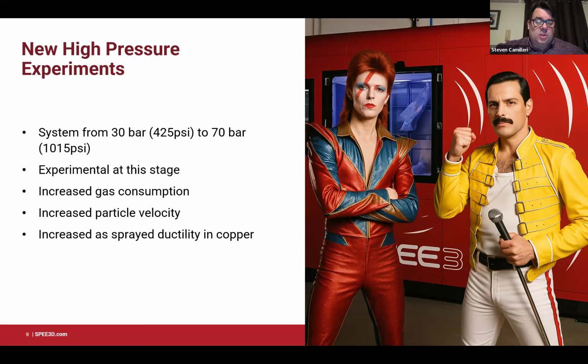So our normal cold spray system operates at 30 bar, about 400 PSI. And we've decided to push things this year. So there are people demanding better properties as sprayed from our process for different applications. So we've decided to try implementing a high pressure system. Typically we run off a compressor at about 30 bar with compressed air, and we decided to more than double that to 70 bar.